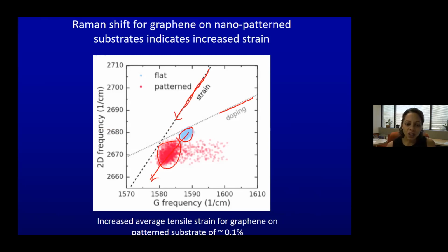Now there's a little bit of doping out here. That's because we got some charge effects from our fabrication, but the bulk of the material really moved along the strain line. And so this tells us that we are indeed straining the graphene that's on top of these nanopatterns. It's moving mostly along the strain line. The strain is different from on flat. By flat graphene, I mean that we always have control samples that are not on pillars. Okay, so the control samples that are not on pillars are less strained than the samples that are on pillars. And we can also calculate that we get an average strain of 0.1%, but this is averaged over the whole thing, which means at the apex, we could have a much, much larger strain.